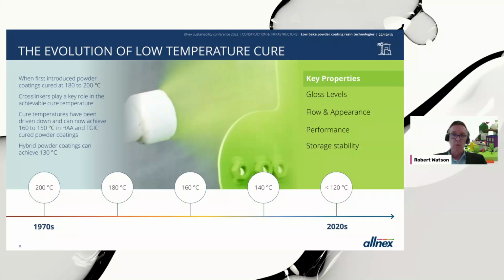Now, what's important to remember is the role that the cross-linker plays in the achievable cure temperature. And we can almost think of a chemical dance. We've got the two partners, the cross-linker and the resin. And you can imagine that if one of those partners gets a little bit old and a little bit slow, then the dance becomes a little bit old and a little bit slow. And it's important to note that within the powder coatings industry, there hasn't really been any significant new cross-linker developed for about 30 years. And that last one was hydroxyalkyl amide, HAA, which is a very important cross-linker for the